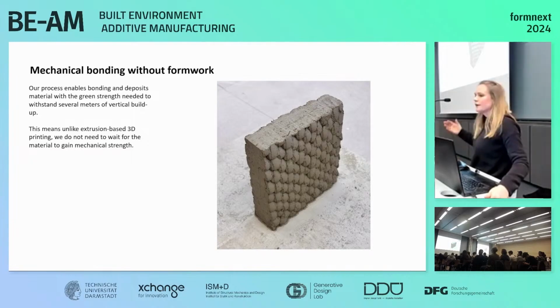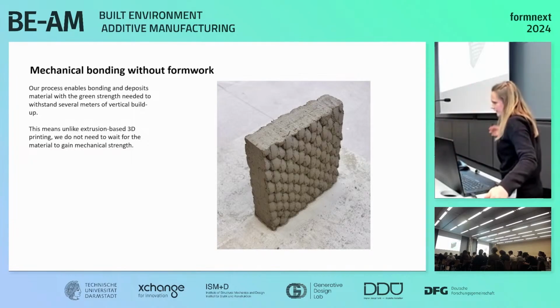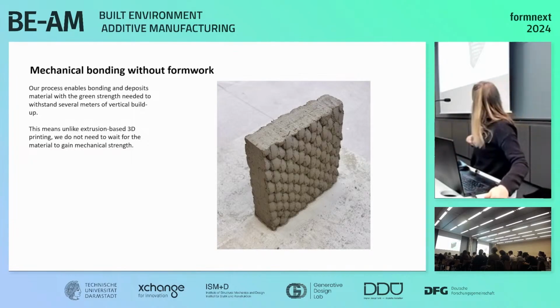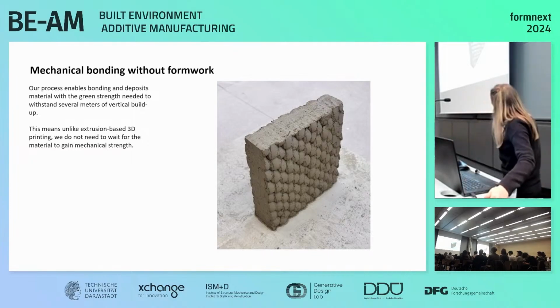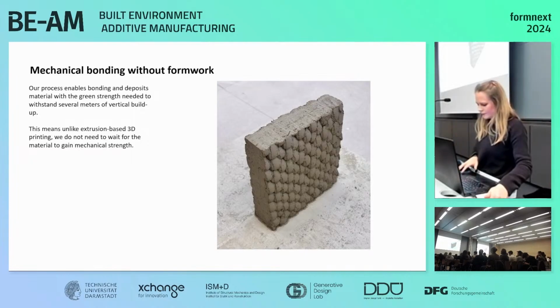But we don't need that because we can basically take very dense materials and we can precisely control how fast we deposit them. And with this, we can actually deposit material with a high enough yield stress that it already can withstand several meters of vertical buildup. So this is a huge benefit for additive manufacturing because we basically aren't relying on the rapid curing and the rapid green strength development of a material.